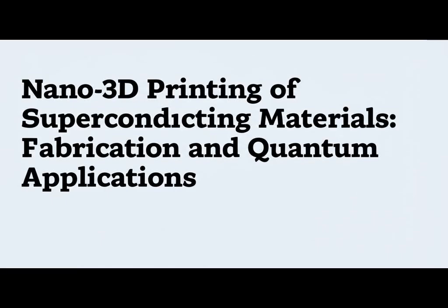So, how exactly are scientists performing these microscopic miracles? Several cutting-edge techniques are in play. For instance, there's focused electron beam-induced deposition, or FEBID. This uses a focused electron beam to decompose precursor gases, depositing superconducting material onto a substrate with incredible precision, down to 10 to 30 nanometers. This allows them to create intricate 3D shapes, like nanowires and even tiny nanohelices.